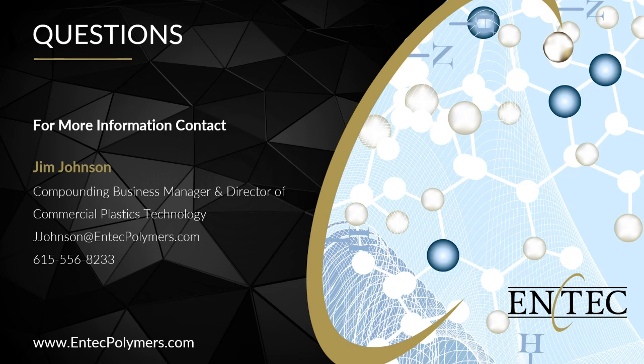Another question that came in, what is the best type of OBC you recommend for a high density polyethylene and polypropylene blend, and what is the usual loading level? The product there is the Dow Infuse OBC, and this is a polyethylene block copolymer. For compatibilizing the high density polyethylene to polypropylene, it depends a little on the ratios, but we've seen really, really good success around that 6 to 7% loading level. Once again, it doesn't mean that a lower level would not compatibilize your specific application, but generally speaking, I would tell you to look at a 5 or 6% level.